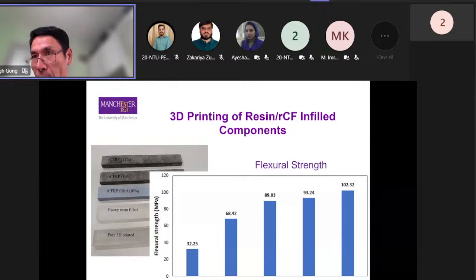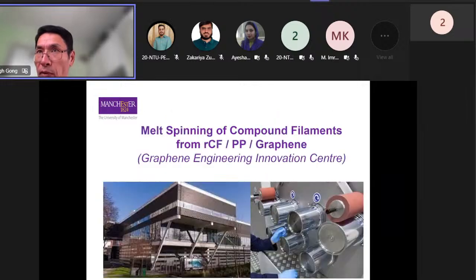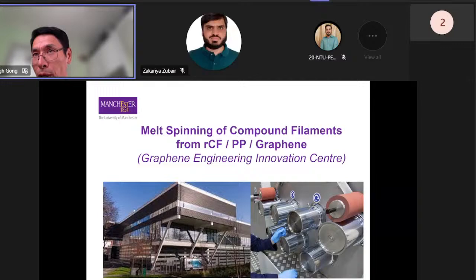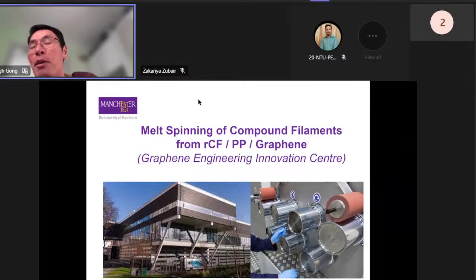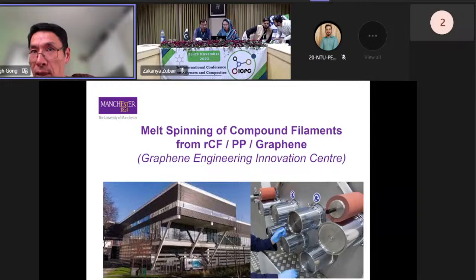And we find that with recycled carbon fiber filling, we can actually improve the strength of the 3D printed parts. So that's very promising. The other one is to use compound spinning by mixing the recycled carbon fiber dust material with polypropylene and then spin it. We also try to mix it with graphene. Of course, we are in Manchester, so we are using graphene in almost everything nowadays anyway. And this is done in collaboration with the Graphene Engineering Innovation Centre, which is on campus.